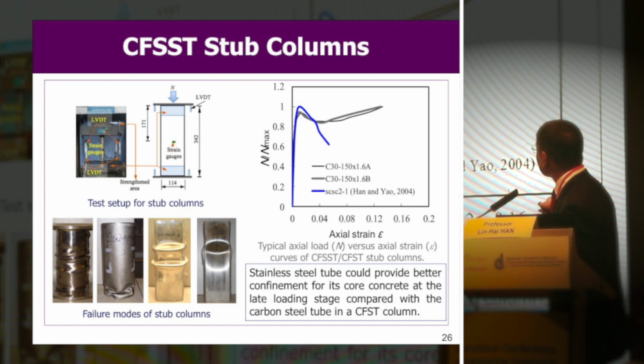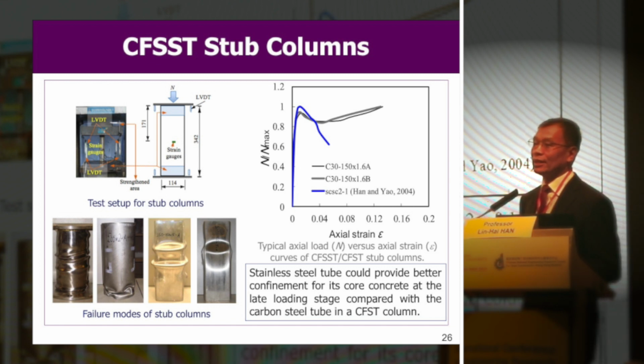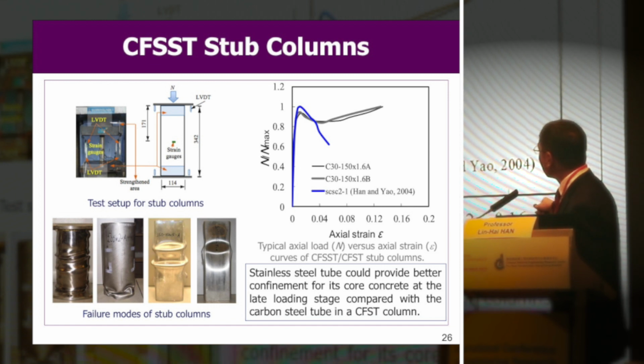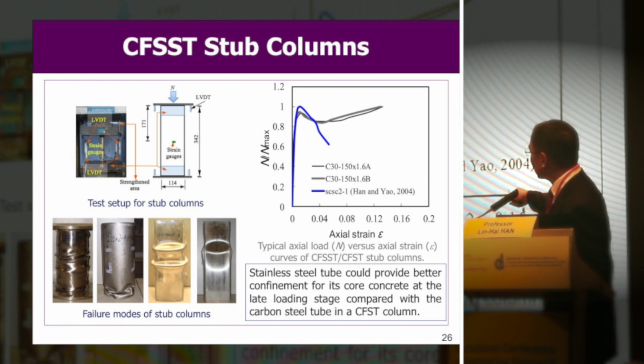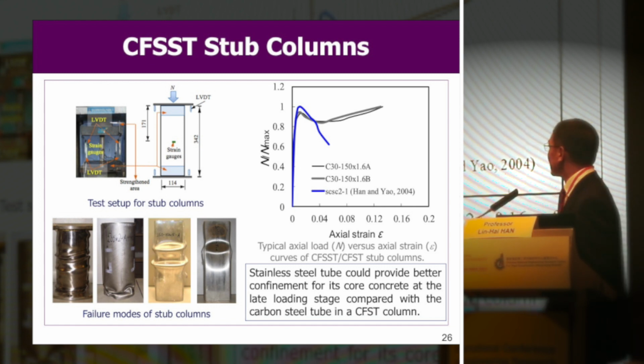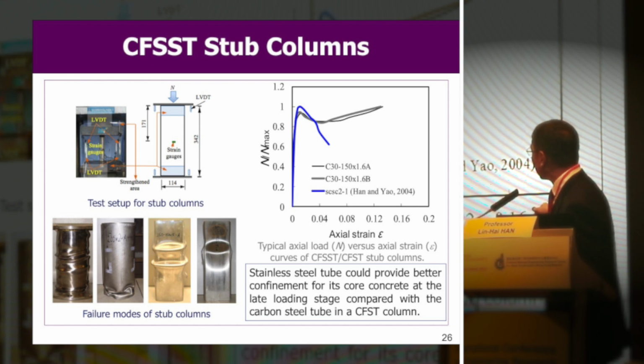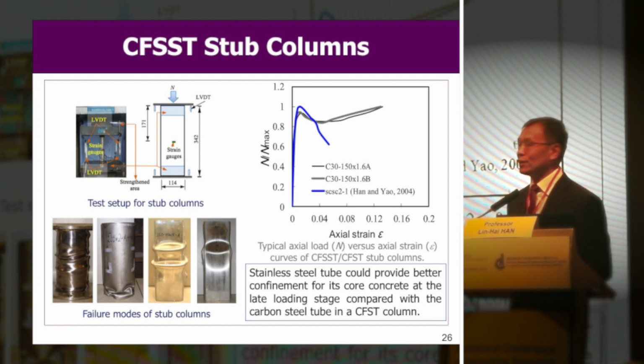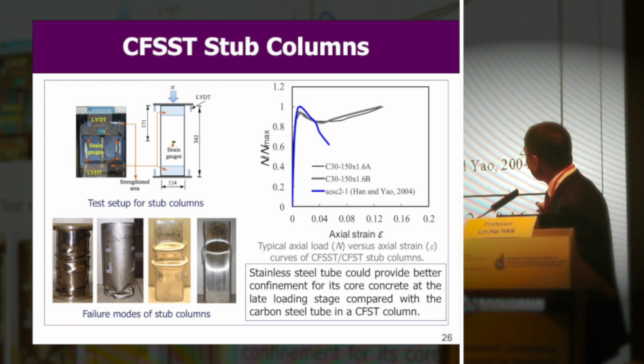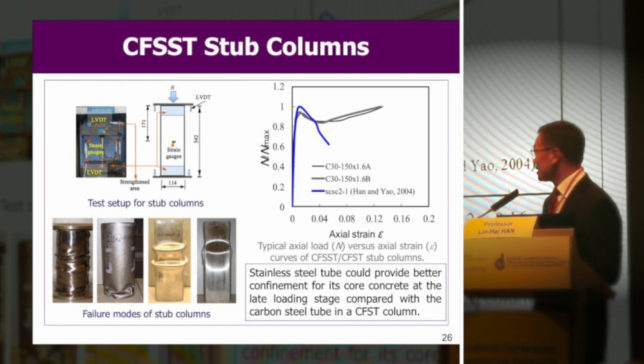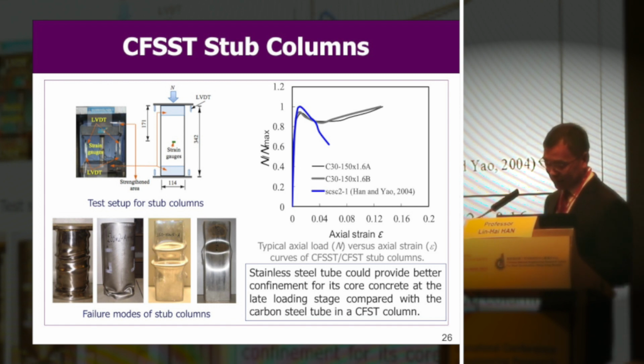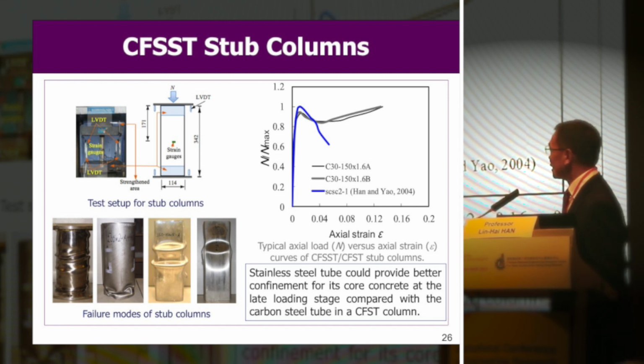You can see this actually is a carbon steel tube filled with concrete. This is stainless steel tube. So if we put the numerator as the maximum strength of the curve, you can see for the stainless steel tube, the curve goes like that, to a point declining and then increasing because of hardening of the steel. But for carbon steel tube, to the peak and then to decline. This is because of the different material properties; actually austenitic stainless steel tube was used for these specimen comparisons.